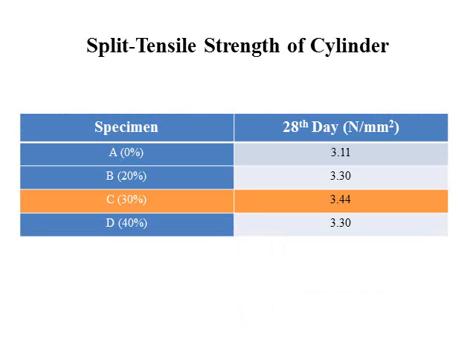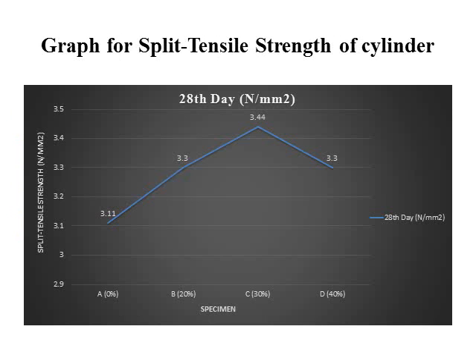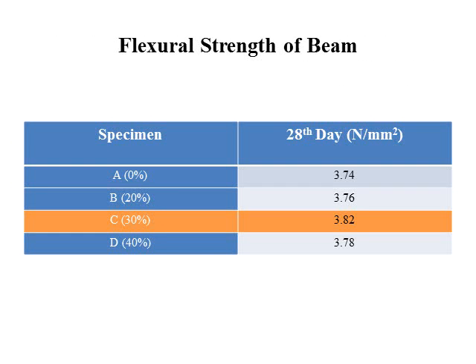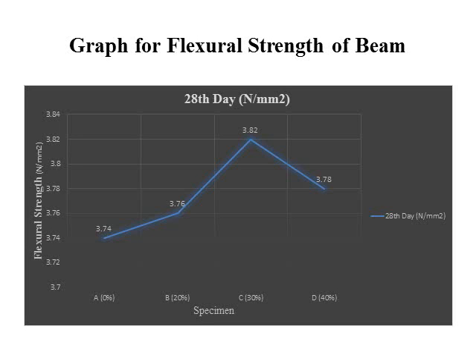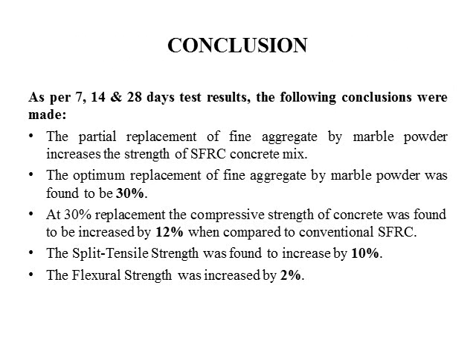Testing on cylinder and beam. Cylinder and beam were tested only for 28 days, and the maximum value was found at 30%. The maximum peak value is 3.44 Newton per mm square. This is the graph showing the peak value. Flexural strength of beam also increases at 30%, and the peak value is 3.82 Newton per mm square, and the graph shows the peak value.